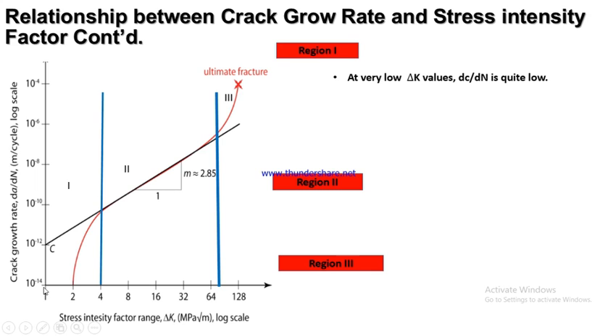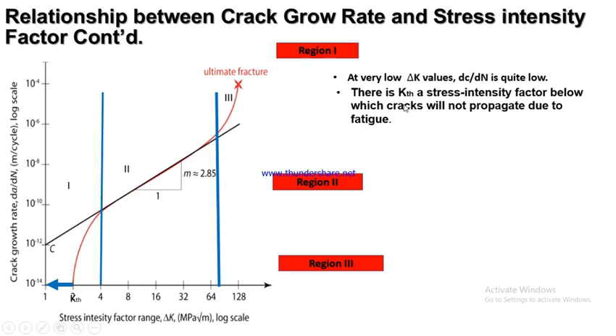You can see basically we're starting from 1 to 4. Then there is a particular threshold of stress intensity factor: when the crack in the material is below this stress intensity factor, there is no amount of cycle that can cause fatigue, and that material can never fail by fatigue. That is, if the crack is below the stress intensity factor, between this particular region and this particular region, there is no amount of cycle that can cause fatigue in that material, and all these are happening in region 1.